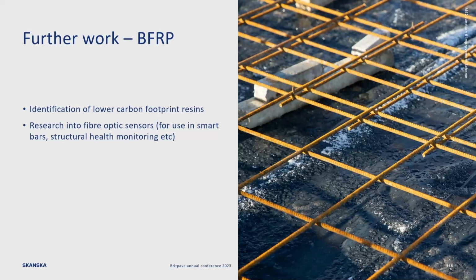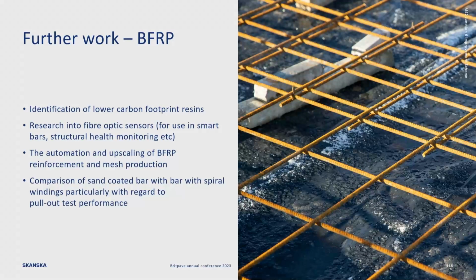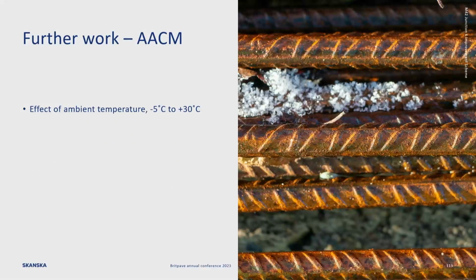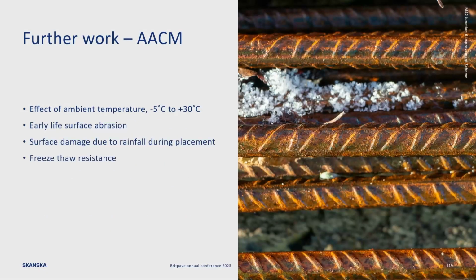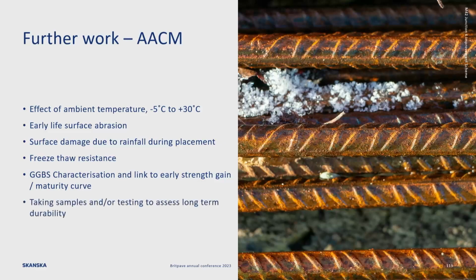So on that point, and I won't go through every item in detail verbatim, pull-out tests with varying reinforcement diameters and embedment depths, and also looking at the difference between sand-coated and the spiral windings, I think are really important. And there are steps we can take, perhaps introducing a lower carbon resin. That's really where a lot of the carbon sits with the resins used in this product. And with the AACMs, we have to understand not just longevity, but how it performs in different temperatures, extreme cold and hot. Early life surface abrasion is one area where we saw some issues. But I think there are some major steps that the industry can take.